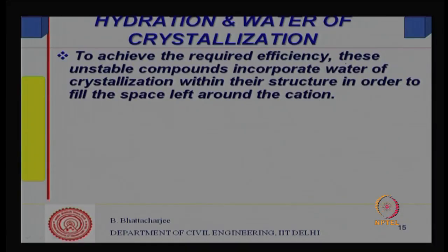To achieve the required packing efficiency, the unstable compounds incorporate water of crystallization within their structure in order to fill the space left around the cation.